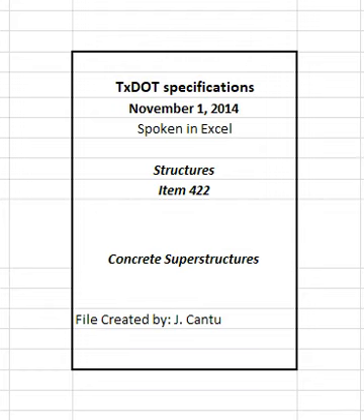Follow the sequence of placing concrete shown on the plans or specified. Do not place concrete when impending weather conditions would impair the quality of the finished work. Place concrete in early morning or at night or adjust the placement schedule for more favorable weather if conditions of wind, humidity, and temperature are such that concrete cannot be placed without the potential for plastic shrinkage cracking. Consult the evaporation rate nomograph in the Portland Cement Association's Design and Control of Concrete Mixtures or the evaporation rate spreadsheet available on the department's website for shrinkage cracking potential.